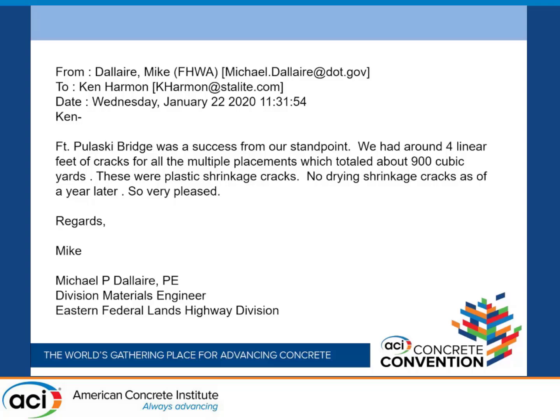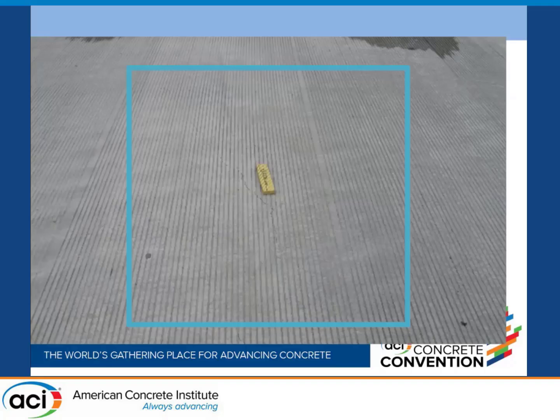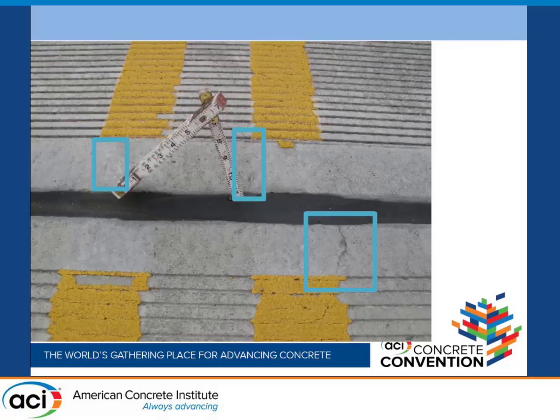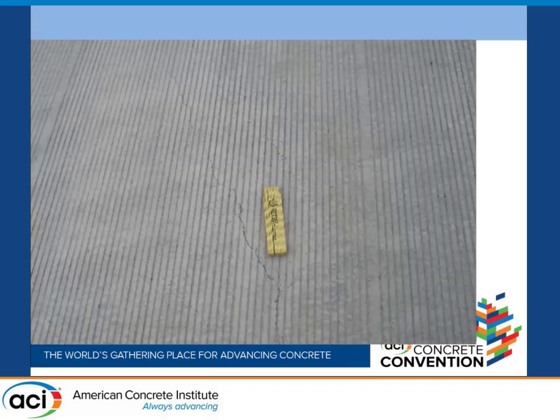So very pleased. Well, shortly after they sent this, at 14 months, they did another crack survey, and they did find an additional 3 feet of cracking in the second span. But total, this is 7 feet of cracks, cumulative. They did another survey at 28 months and found some small cracks that radiated from the joint at the 11th span. And so a total on the whole bridge, if you add all the cracks up, was about 10 feet. And 10 feet of cumulative cracks for a 35,000 square foot bridge deck is not bad.